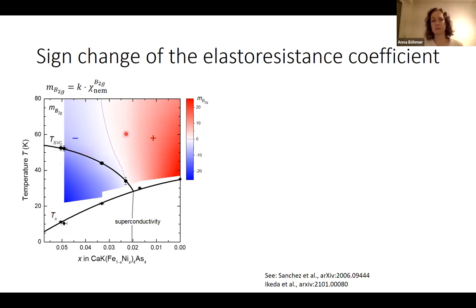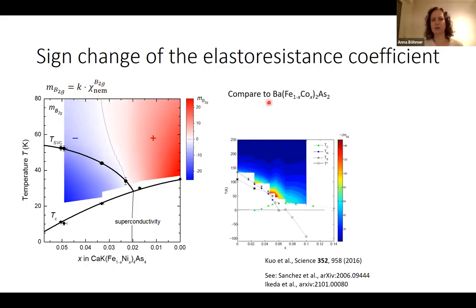We see a sign change, but the nematic susceptibility does not change sign. This has to be the proportionality constant. If we compare that to the cobalt barium 122, there's no sign change here, but there's a significant change of magnitude of this elastoresistance coefficient. And the influence of this prefactor was just recently discussed, well, just 10 minutes ago in the talk and these recent papers. So here we have a case, there's not only a magnitude change,